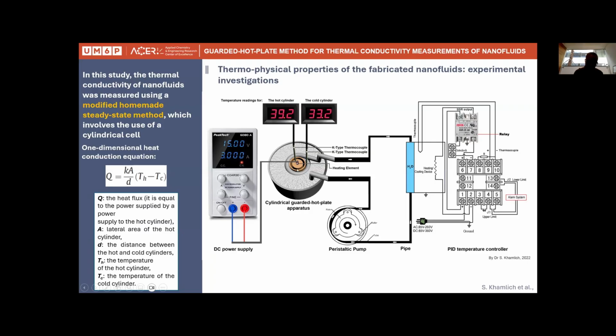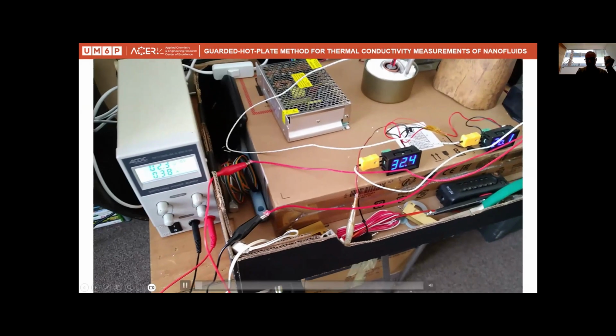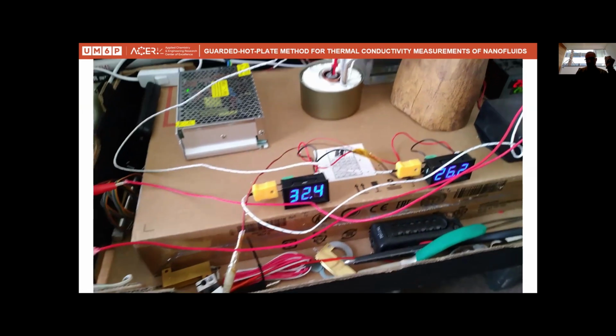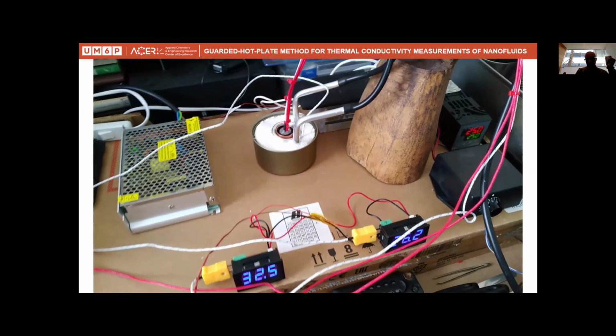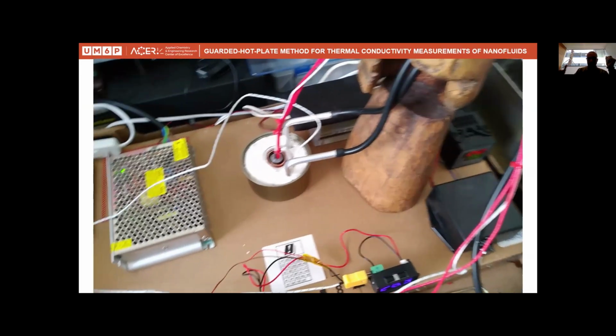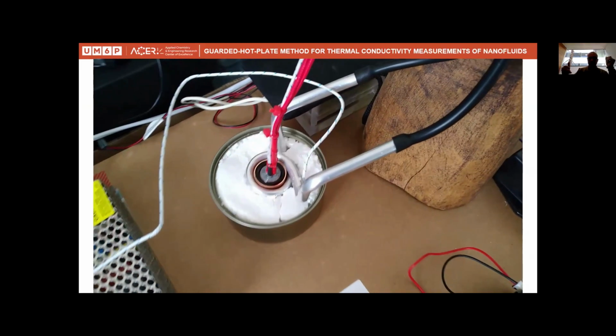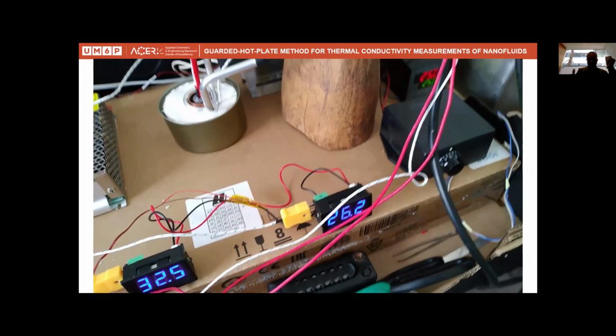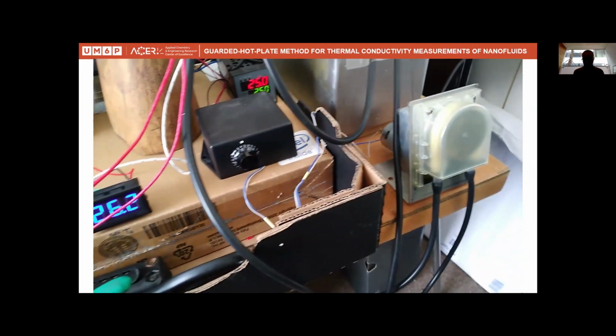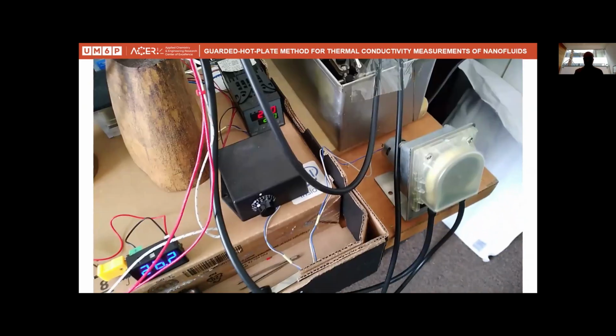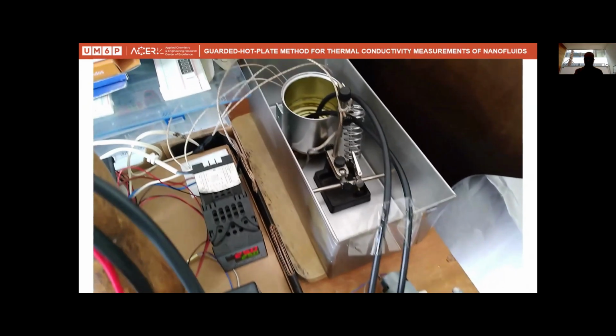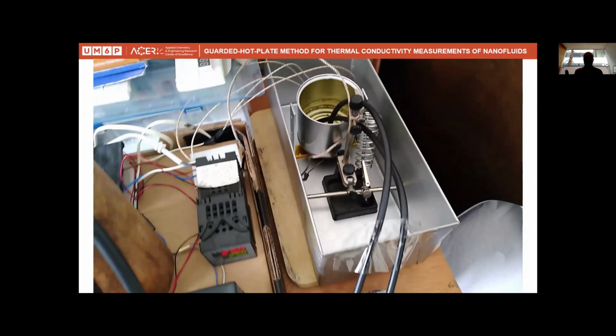It shows you that if you have applied a power, which is Q here, by using this power supply, the equation is that the power equals the thermal conductivity times the area of the inner cylinder, divided by D. D is the distance between these two cylinders, the inner and the outer cylinder, and you can measure the hot plate temperature and the cold plate temperature, as you can see here, so you can extract the thermal conductivity. Very simple. So we built it at home, as I mentioned, and we produced nanofluids, they were analyzed, and really we found some beautiful results for different nanofluids with copper, with aluminum oxide, with even some complex systems. And we published a number of papers on this research. And really we are trying even to enhance the measurement by implementing and getting even better instruments.